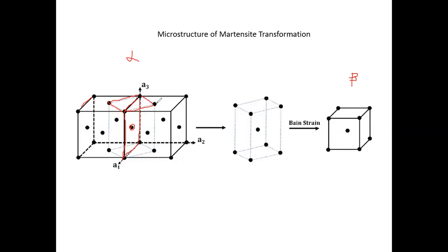This square is defined by the two vertices of the original cube and the particle at the center of one cube and the particle at the center of the other cube. So this is the square. If we consider the edge length of the cube originally is A, I think this diagonal is A, right? For this square, this one is going to be the diagonal, and the edge length of this is going to be square root 2 over 2 times A.